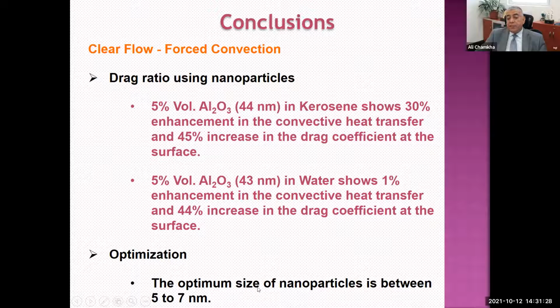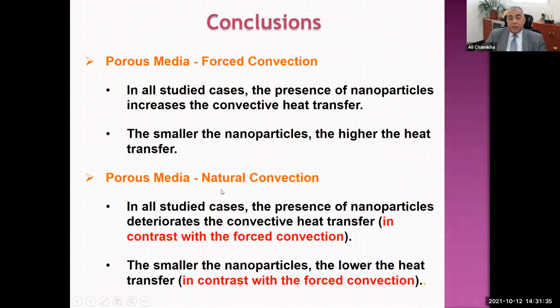Optimization: the optimum size of nanoparticles is between 5 to 7 nanometers for these studies that we did on boundary layer. In porous media, forced convection, in all studied cases, the presence of nanoparticles increases the convective heat transfer. The smaller the nanoparticles, the higher the heat transfer. So smaller nanoparticles are better in this case.